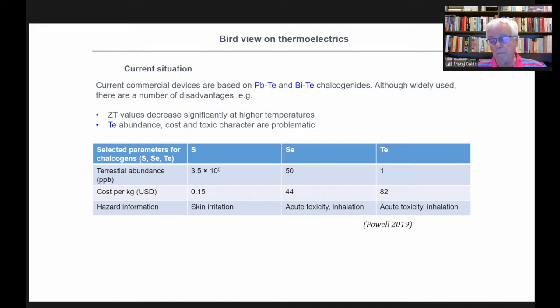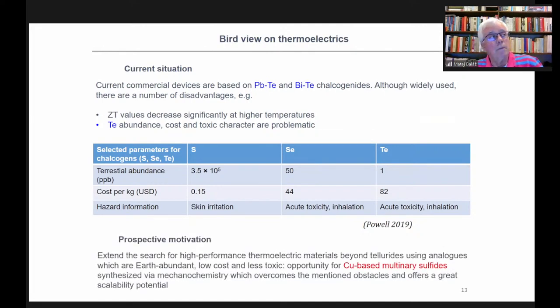So there is time for motivation, what to do next. Of course, it is important to extend research to looking for high performance thermoelectric materials beyond tellurides, using analogs which are earth abundant, low cost, and less toxic. In this case, there is good space for copper-based multinary sulfides which were synthesized via mechanochemistry, and they overcome the mentioned obstacles and offer great scalability potential.